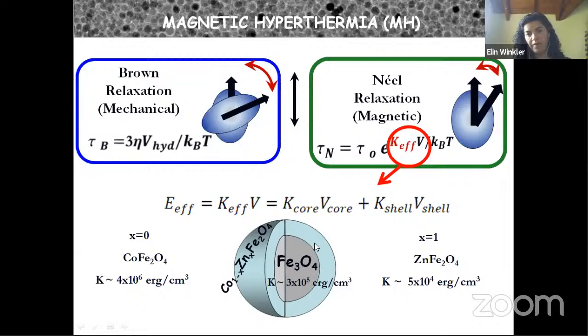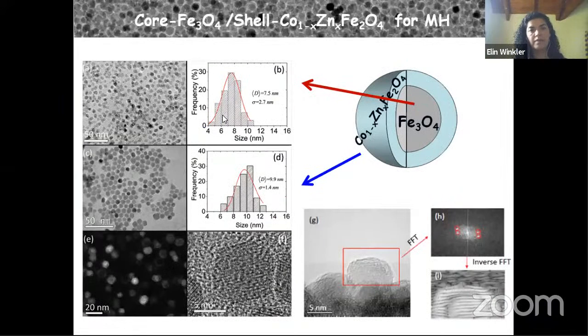And again, we fabricate a magnetite core and we encapsulate it with cobalt ferrite. The cobalt ferrite has an anisotropy of 10 to the 6, and we systematically replace the cobalt by zinc, and we reduce the anisotropy two orders of magnitude. In that way, we can change this relaxation time a lot compared to this one. Well, we did that. Here there are some TEM images. The core nanoparticle has 7.5 nanometers, and the core shell approximately 10 nanometers. And here you can observe the core shell structure.